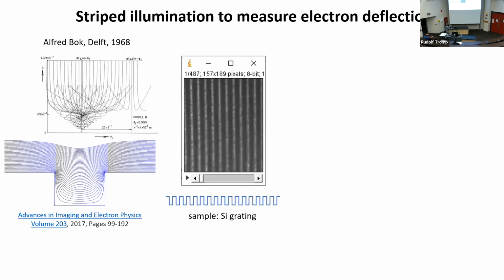That's an experiment we can do. Instead of just a single trench, we take a silicon grating. And if we form an image with the electrons turning around, say 2/10 of an eV away from the sample, 20 nanometers, and we go in an under focus condition, we see these bright lines, which correspond to the trenches here, right? Now, what if this is just with uniform illumination, right? Broad beam illumination, like you would do in TEM.